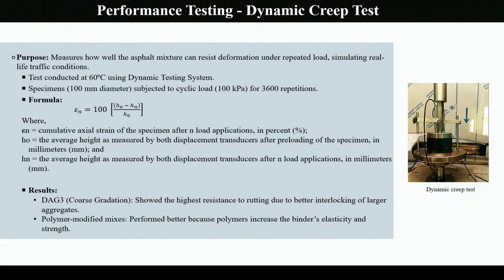In this, a dynamic load is applied, like how the wheel load is coming and going. For 1 second the load is applied, and for another second the load is removed. So after around 2 hours, we have the initial height of the sample, and thereafter we note the final height, and with the help of the change in the deformation, we are able to calculate the permanent strain. So for the considered different design factors such as aggregate type, aggregate binder type.